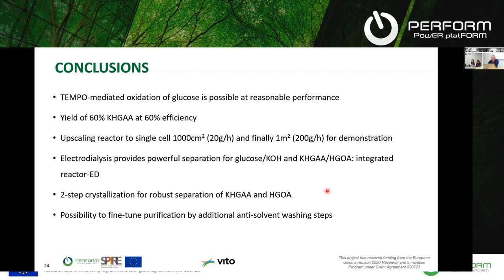So in conclusion, for the first part of the reaction, the oxidation of glucose, TEMPO is a well-performing electrocatalyst. It is a mediator, of course, and needs to be recovered. But we have reasonable yields and efficiencies, and we're able to also scale up to 1,000 square centimeter, which is approximately 20 grams per hour. And both the electrodialysis and the two-step crystallization with the anti-solvent precipitation really make it a powerful downstream processing, when the process can be used in a sustainable way such that it will not provide any significant waste streams.